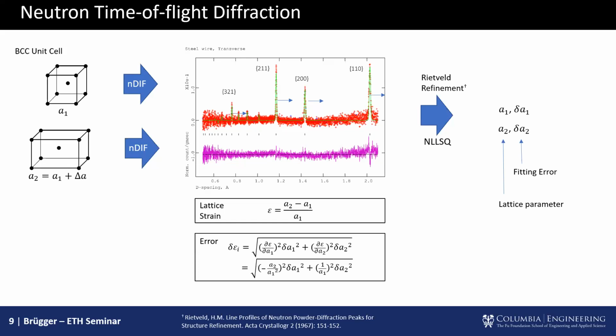And of course, the holy grail right now, and this is not fully realized yet but people are working on it, is that you would want to take your, say, monolithic material that has been 3D printed, stick it into a goniometer, spin it, take multiple reflections, so multiple shots at different angles, and then reconstruct the full strain tensor. So tensorial tomography is something for which we don't have a general solution. If we have very clean boundary conditions, very clean assumed loadings, we can get pretty good at this. But if we're looking at residual stress fields that are not well defined outside of a boundary condition driven system, then that's still something that has not been achieved. But that's an area where AI is now being employed. We're hoping we get something.